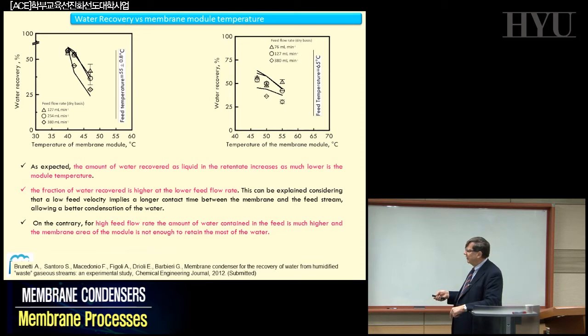What is happening here is that the amount of water recovered as a liquid in the retentate increases as the temperature is lower. If you are decreasing temperature, condensation is increasing, and the fraction of water recovered is higher at the lower feed flow rate. That means you are increasing contact time, and you are just increasing the amount of water recovered.